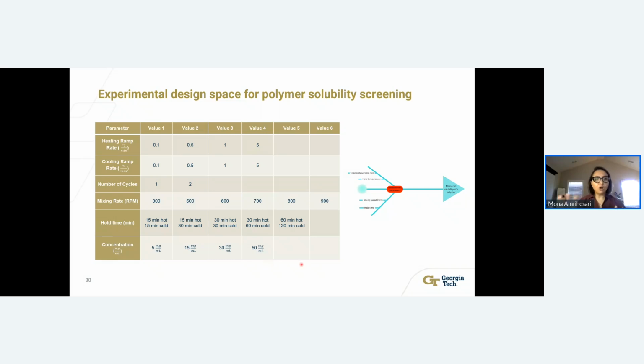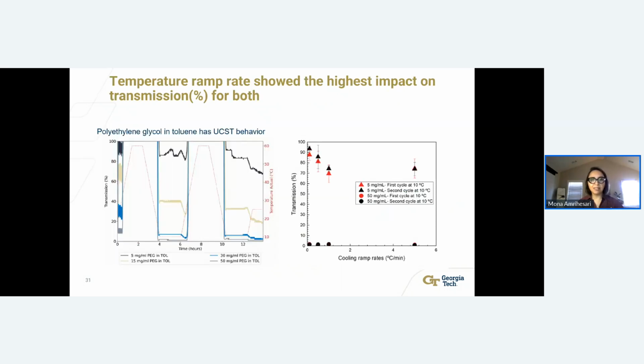So looking at all these variables and trying to standardize our method, I will cover some of the findings that led to how we ended up with the standardized method that we went with. For this study, we looked at the transmission percent during the isothermal hold. So this is the example of polyethylene glycol in toluene. We picked two polymers in the same solvent. One has a UCST behavior and the other has the LCST behavior, which I'll show in the next slide.